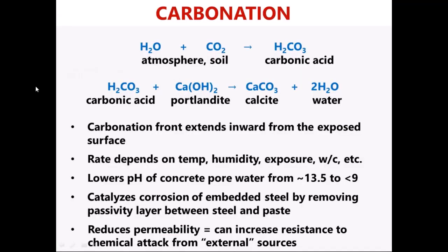All right, let's switch gears briefly here and talk about another facet of the concrete we can identify and work with in petrographic analysis, and that's to determine if the concrete is carbonated or not. So carbonation of the concrete results from the formation of carbonic acid, H2CO3, from water and CO2 that's in the atmosphere, it's in the soil, it's everywhere.